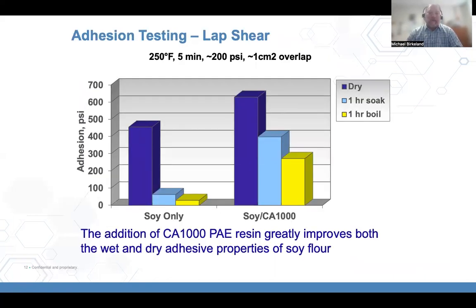So if you take a look at soy on its own, again, you can formulate it to be a pretty good dry adhesive, but once it gets wet, it falls apart pretty quickly. Here we see some lap shear data. Taking just the soy, you've got a decent amount of dry strength. As soon as you soak it or boil it, you lose pretty much all of your strength. And the addition of a PAE, this particular one is a CA1000 PAE resin, it greatly improves both the dry and the wet strength of the soy flour, and really gives you an opportunity to be able to bond and hold that bond in a wet type of a test.